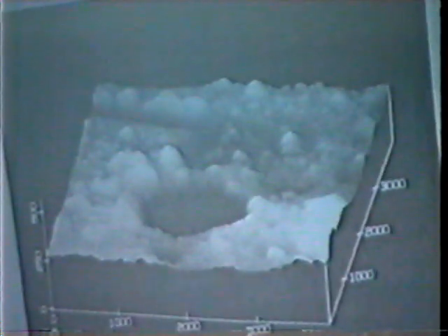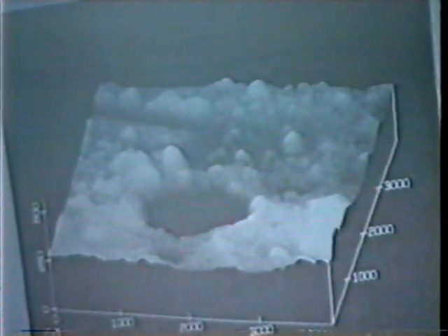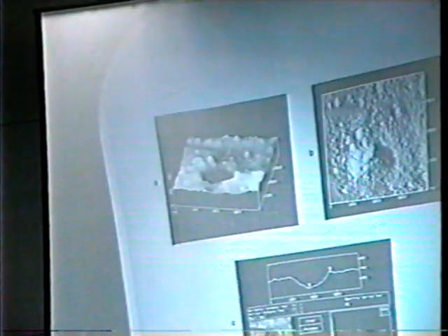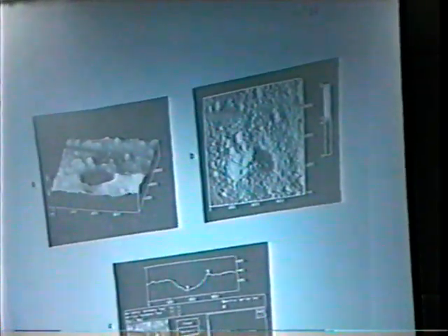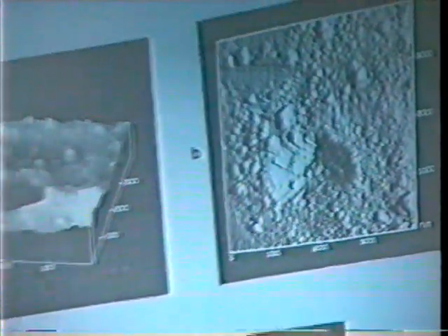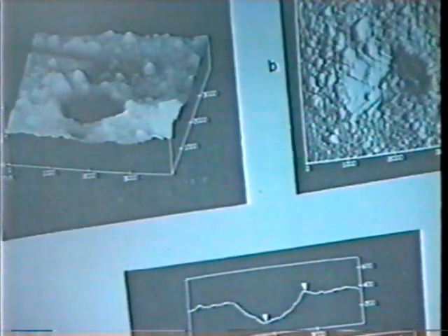So years ago, we reported hot spots in palladium. So here's what we think a hot spot in palladium looks like. We published this. This is atomic force microscope work. So it looks like this with radial lines. Our interpretation is this spot melted, exuded some material, and then recrystallized.